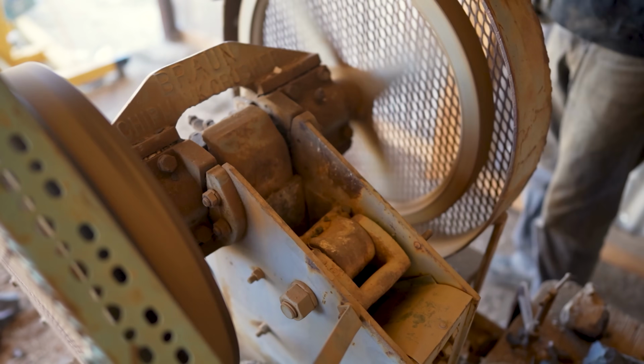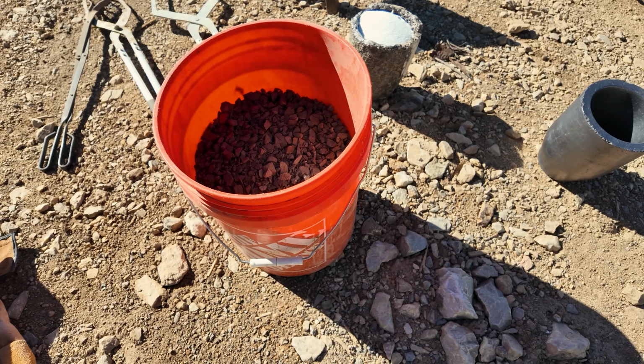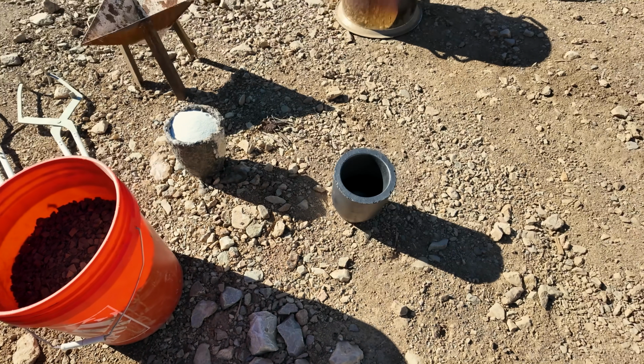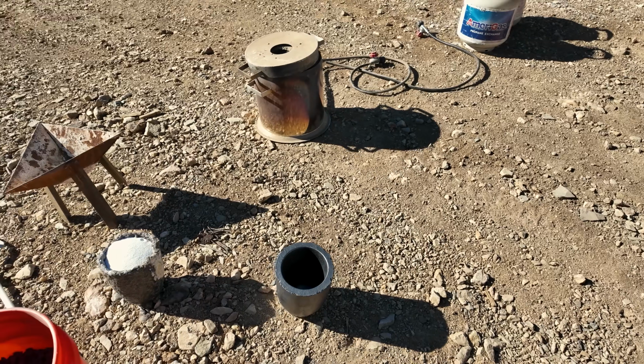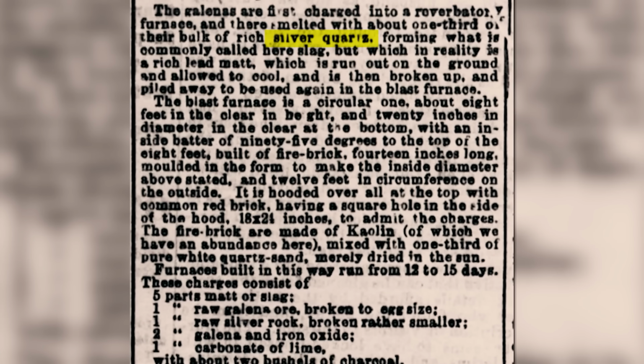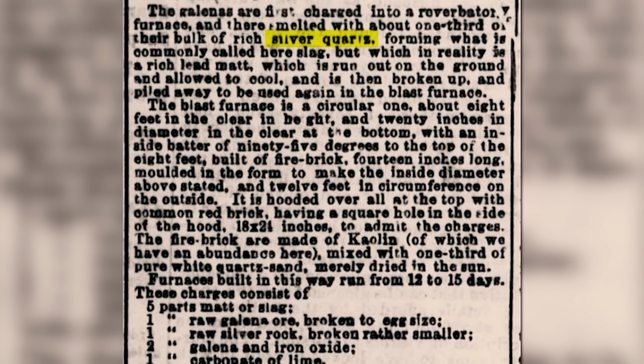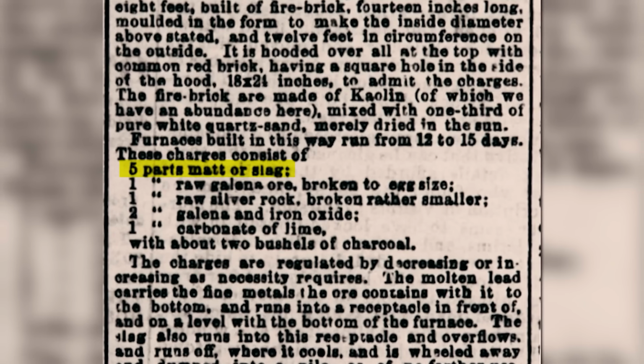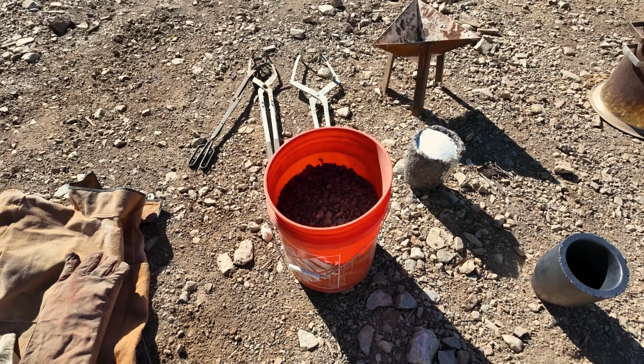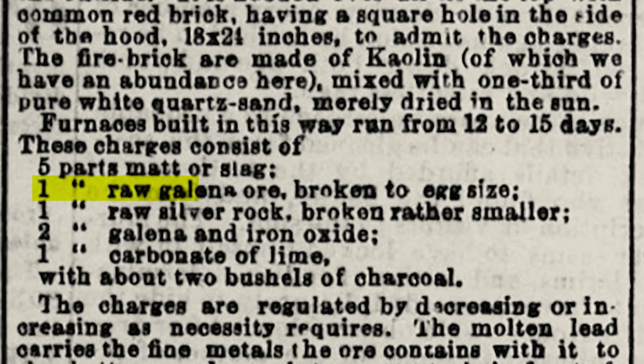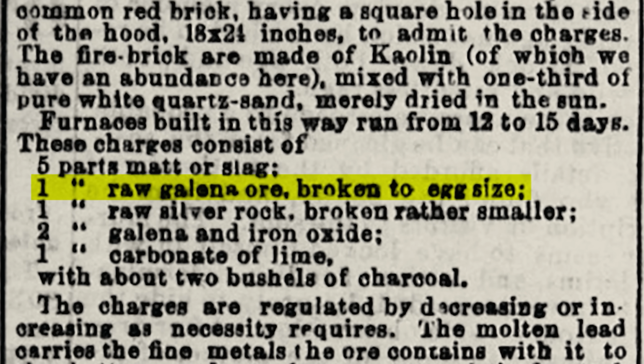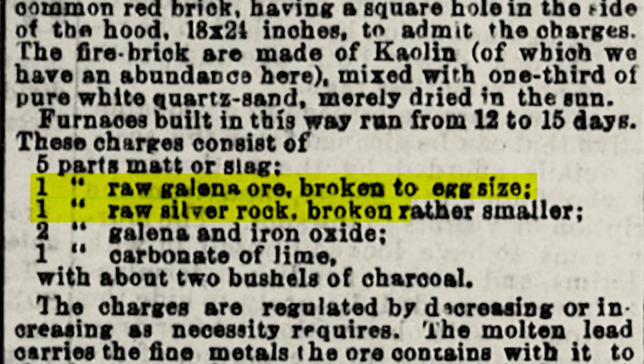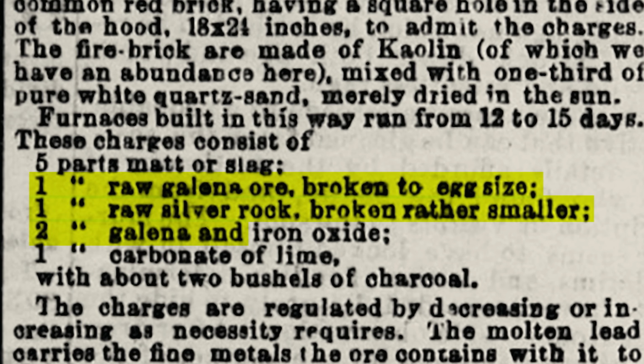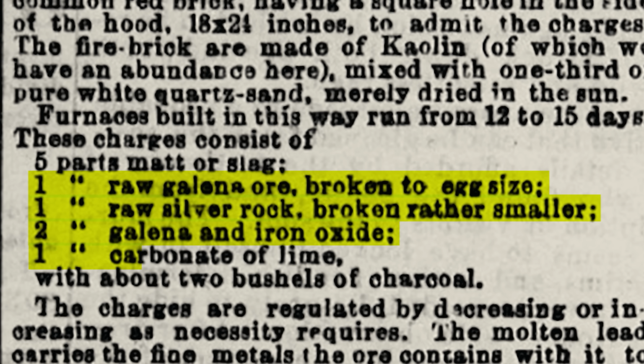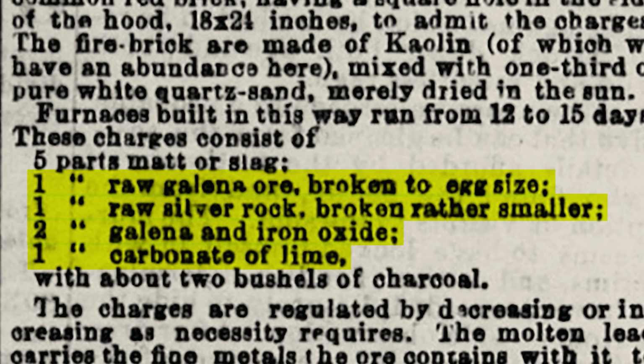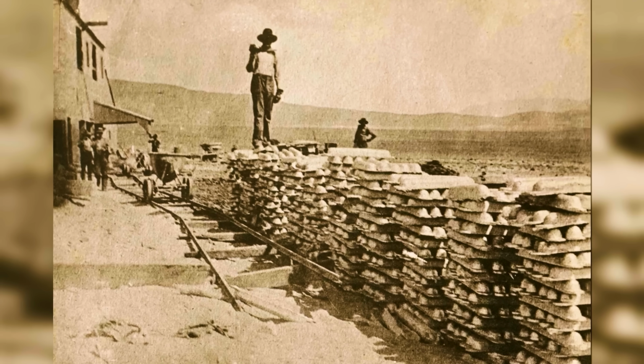So we have the slag crunched up once again. I have my other ingredients that we're going to use for the smelt. And back in 1870, there's a newspaper article from up here at Cerro Gordo that shows the exact recipe that they were using when they made this slag. And that one shows 1 part raw galena ore broken into egg size, 1 raw silver rock broken smaller, 2 galena and iron oxide, 1 lime calcium carbonate, and they would end up with these 80-pound pigs, these bars.